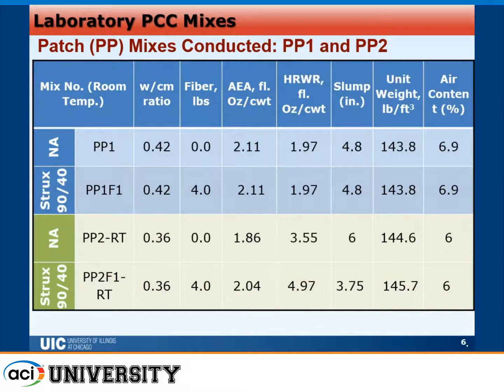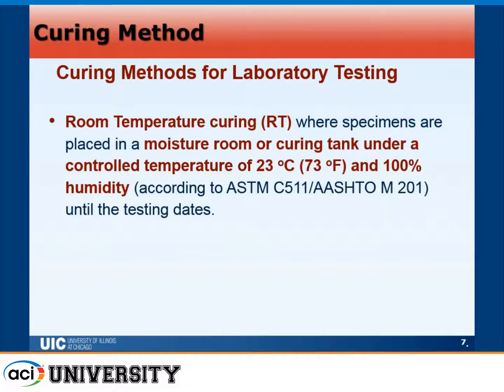to see. For the patches mixes, PP1 and PP2, we also took into consideration the effect of Strux 9040 fibers at 4 pounds per cubic yard, and PP2F1 Strux 9040 also at 4 pounds. And you can notice here that the water to cement ratio in the PP2 case is smaller, as a higher strength is expected or is required at the time of opening to traffic. The curing test methods in this study, we considered room temperature under 100% humidity.